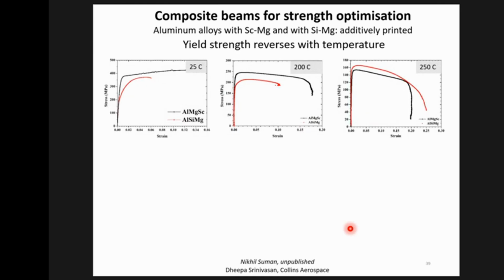There's an interesting consequence of this load shedding, and I'd like to illustrate that with this particular example, where we have two aluminum alloys. They're made by additive manufacturing, laser powder bed fusion. One is a scandium magnesium alloy, which is extremely strong at room temperature, and the other is an aluminum silicon magnesium alloy. So if you look at the room temperature behavior, the black line here is the magnesium scandium, which is much stronger than that of the silicon. But by the time you get to 250 degrees, it reverses.